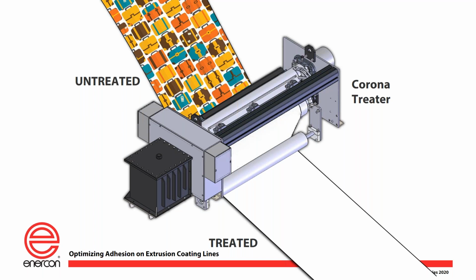So you could also look at it this way, right? The film comes to the treater in a manner where you have all this baggage, meaning additives and surface contamination and maybe even some age to it. Maybe the surface of the material, because of its age, has a bunch of crystals on it. It's just not really suitable for converting. You couldn't really get any sort of adhesive coating, whether it's extrusion coated or even a standard adhesive coater. You couldn't really get that chemistry to work on that surface. And what the corona treater does is remove that baggage from the surface, clean it, and functionalize the surface so that in the converting process, we're all set to go. Next slide.